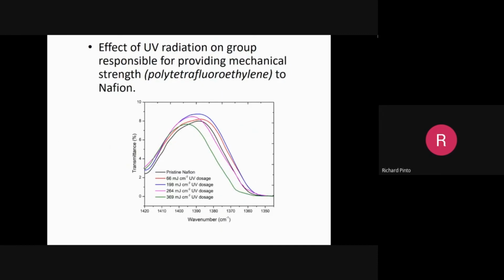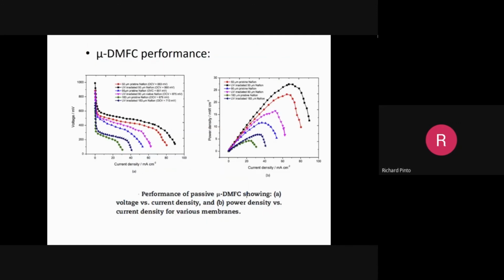Effect of UV radiation on the group responsible for providing mechanical strength. This is another thing which we used. Also, the benefit of UV exposure: increased porosity, but also increased cross-linking, and increase in the mechanical strength. That is what we have found there also. So 198 mJ cm^-2 UV dosage, you see the peak here, 198. Mechanical strength is increased. There is a small difference, but still it is significant. Mechanical strength also is increased, which is important for long-term durability of the membrane.